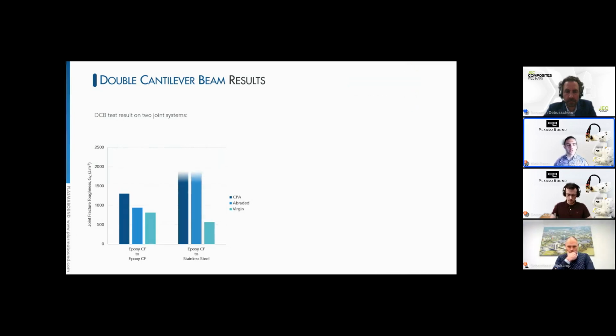When it comes to the epoxy to stainless steel, however, we match or equal the abraded version, and again, the virgin is lower. The reason for this is that the failure in this case, the adhesive failure, occurred along the stainless steel line, and also the sudden increase in the stiffness should be taken into account, the fact that it's an imbalanced DCB system, where there's an epoxy bonded to a dissimilar material, a stainless steel system.